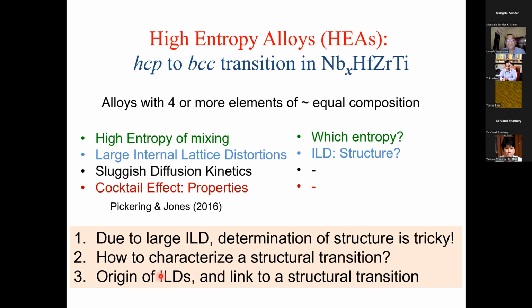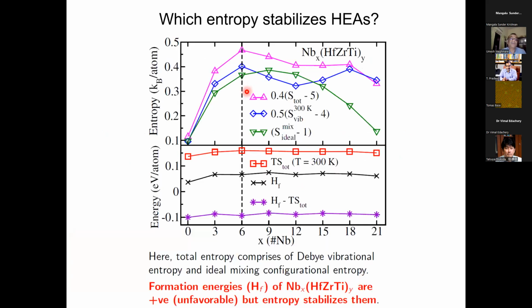So what we decided to do is to understand the origin of ILD and then link it to the structural transition. So first, what we show is indeed entropy is large for these alloys. In this case, we are looking at a 4-component alloy. However, the configurational entropy peaks at the equal concentration. The vibrational entropy is the dominant contribution to entropy, and that peaks just before that, and that's what stabilizes.